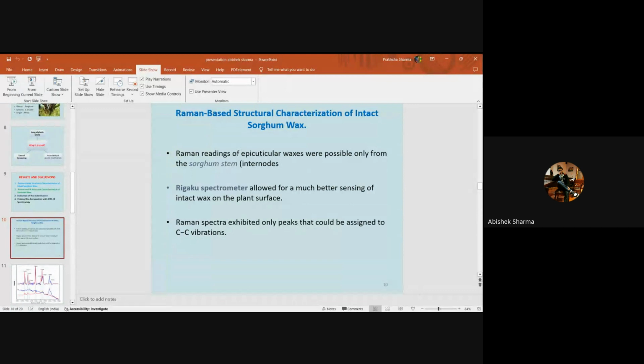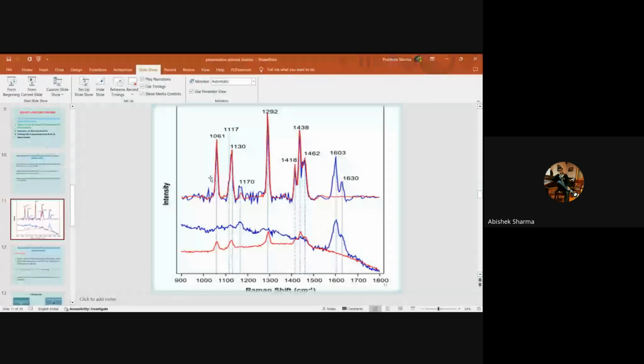Here we can see that the spectroscopy was only possible on the sorghum stem, where a substantial amount of wax was present. In this experiment, the researchers used a Rigaku spectrometer because it allowed much better sensing for intact waxes. And they observed that Raman spectra exhibited peaks only for carbon-carbon bond vibrations. Here, in this graph, we can see that only carbon-carbon bond vibrations are shown. These peaks correspond to carbon-carbon bond vibration.